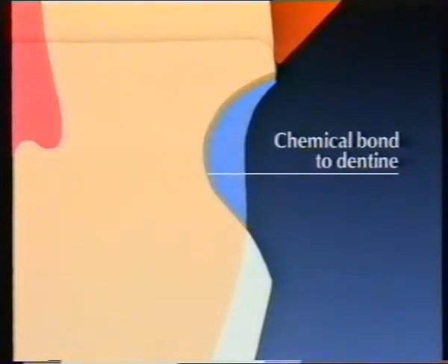The use of glass ionomer as a replacement for dentine is a valuable technique. In this procedure, which is particularly suitable for those cavities where only part of them is surrounded by enamel, the ability of the glass ionomer cement to form an adhesive bond to the dentine and to provide a source of fluoride is used. Once set, the enamel only needs to be etched before a layer of unfilled resin is applied over the cement and the enamel. A composite is then used to replace the lost enamel. A mechanical bond is formed between the set rough surface of the glass ionomer and the composite resin.